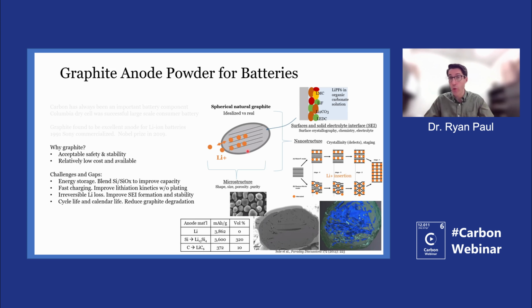So in order to improve the ability to get these ions into the structure, you really have to tailor the graphite at a nano level. Otherwise, you will just end up plating lithium onto the surface, and that just will kill the battery. So all of these really have to be solved in order to move forward.